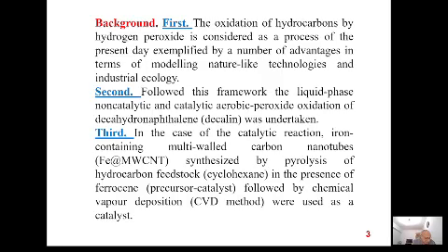While concentrated hydrogen peroxide requires careful handling, it is generally considered safer to transport and handle than gaseous oxidants like molecular oxygen or air at high pressure, or highly corrosive liquid oxidants. When used with specific catalysts, often based on transition metals or zeolites, mimicking natural enzyme systems, hydrogen peroxide can achieve high selectivity for oxidizing a CH bond in a hydrocarbon.